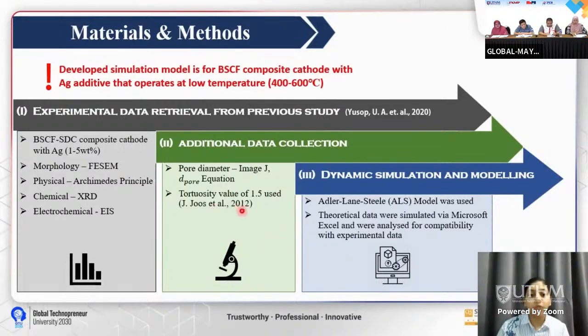And the tortuosity value of 1.5 used refers to the previous author Joos stating that a fine microstructure has a tortuosity value in the range of 1 to 2. So therefore 1.5 has been used, and the third will be dynamic simulation and modeling, which will be the focus throughout my research study. So the Adler-Lane-Steele model was used, and the theoretical data was simulated via Microsoft Excel and analyzed for compatibility with the experimental data of this author, Yusuf Amira.